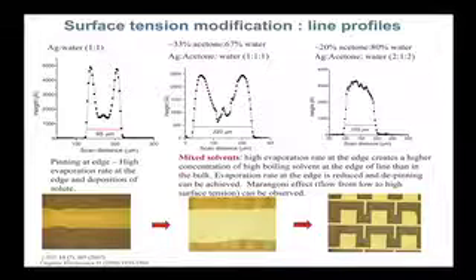So because of that, you get a different evaporation rate at the edge of the drop than you have in the middle of the drop. And that difference in the gradient in evaporation rate creates a flow that brings all the material that you had in your solution towards the edge. On certain occasions, you can get a perfect ring with no material deposit in the middle. And that's really something that we don't want here. I'm sure there are applications that you can look for with this coffee stain effect, but here it is really not what you want.